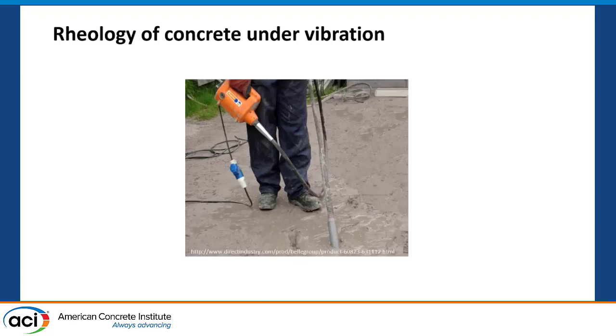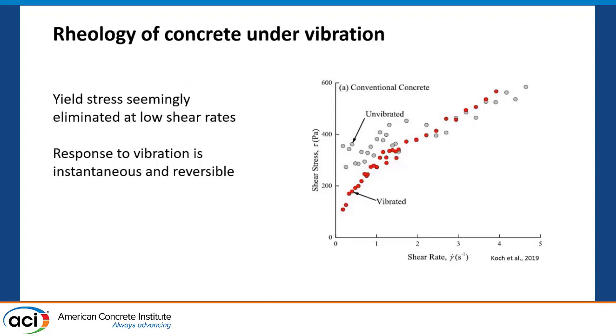This is a known property of granular fluids, not just concrete. All granular fluids react to vibration and there is experimental evidence for this. At very low shear rates, vibration can overcome the yield stress of concrete and the yield stress is seemingly eliminated. You turn vibration off and it instantly regains its yield stress.